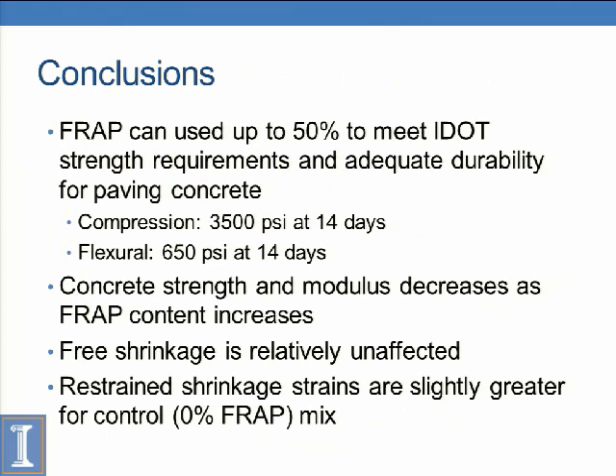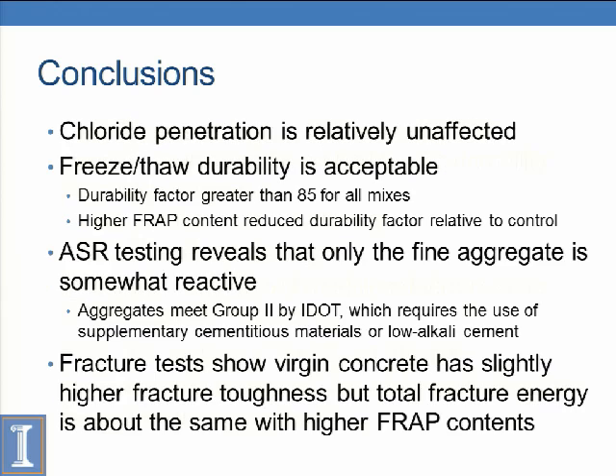So overall conclusions, we found that you can use probably 50% FRAP in your concrete mix without having too much of an effect on the strength and durability properties. Definitely there's a reduction in strength, but durability we found to be relatively the same even though we added FRAP. 50% can meet IDOT's strength requirements for compression and flexural strength. For the most part, we found shrinkage was unaffected, and also with the restrained shrinkage, the strains were slightly greater with the control mix, and we may have higher stress relaxation capability with using FRAP.